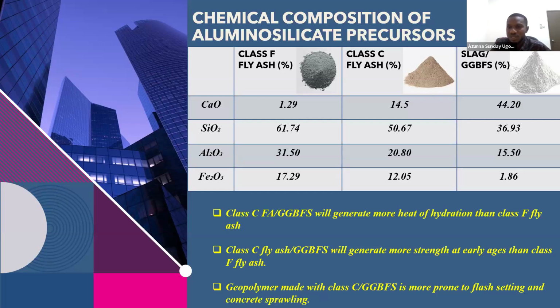Then the calcium oxide content of the slag is above 40% most of the time, 40% up to 60%, even 65%. The silicon oxide in class F fly ash is very, very high, more than 60%. It's the highest of all the binders, while that of the slag, the GGBS, is the lowest. A key understanding of this chemical composition is what is going to determine your mix design. You have to understand the chemical composition of your binders before you know the ratio in which you're going to use them in the design of your geopolymer concrete.